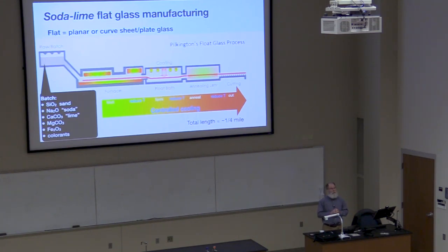Iron oxide, there's always iron oxide in sand. So usually some is added to give a consistent color. And the other thing about iron oxide that I won't go into here is that that is what absorbs the red and the near-infrared light, and that is really critical to how the heat is absorbed in the furnace. So you've got to have some iron oxide in there to melt the glass. And then, of course, for architectural glass and the rear glass of cars, you have other colors in there.